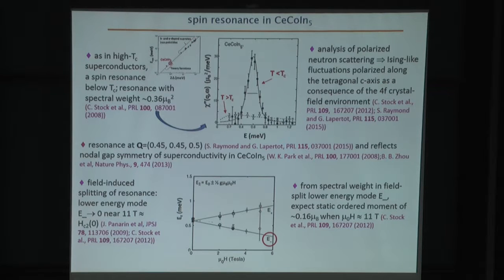More recent neutron scattering experiments have shown that this resonance, while clearly appearing at a well-defined energy, appears also at a very well-defined wave vector, Q, that's equal to 0.45, 0.45, 0.5. And this particular wave vector closely follows the nodal gap symmetry that has been found in cerium-cobalt-indium-5 (CeCoIn5) by both point contact spectroscopy as well as scanning tunneling spectroscopy. So the wave vector at which this resonance appears seems to be a consequence of the particular D-wave nodal gap symmetry of cerium-cobalt-indium-5 (CeCoIn5).